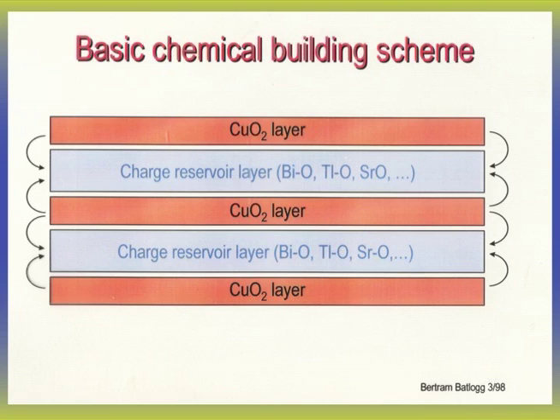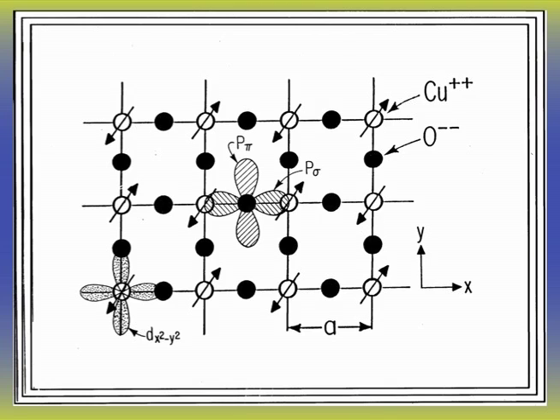And the essence is that the copper oxide layers needed to be essentially perfect, and you did all of the doping via layers which are in between. In fact, almost all of us agree that if we could simply solve the physics of a single sheet of copper oxide, we could solve the problem of high temperature superconductivity.